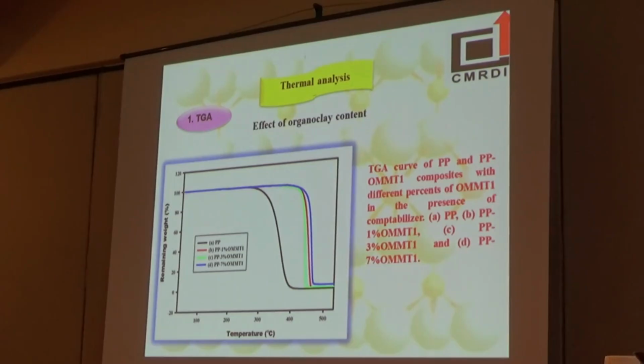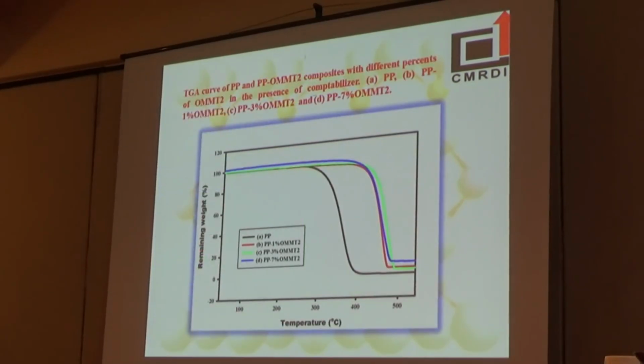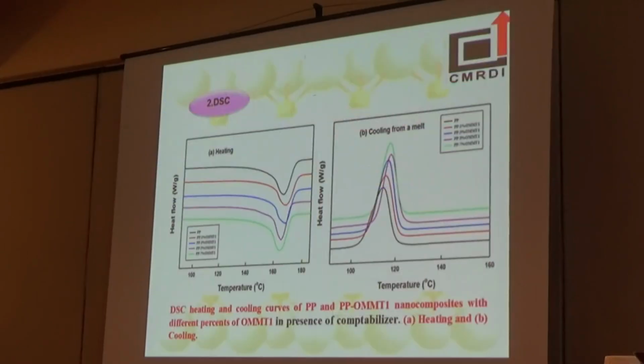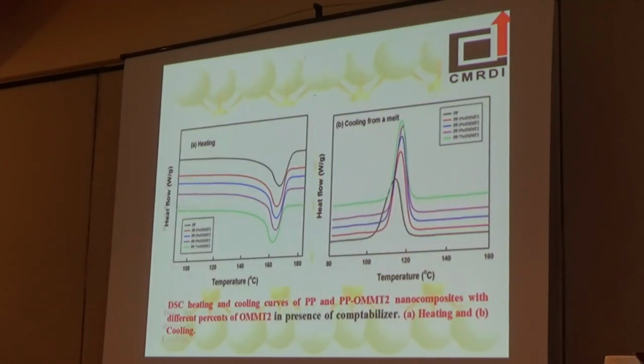Thermal analysis shows that the thermal stability increases by increasing the amount of added organically modified clay. Differential scanning calorimetry shows that the melting temperature decreases while the crystallization temperature increases for all the prepared samples.